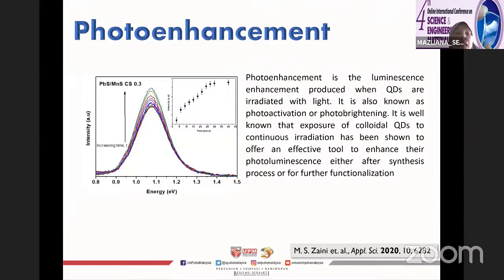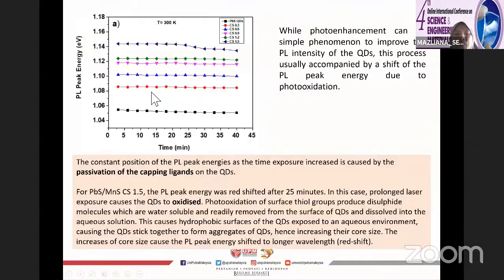samples when we anneal. So we do the photo enhancement. Photo enhancement means you anneal the samples under the laser, and we would like to see the increase in terms of the intensity. And here I just show you the sample of 0.3 monolayer, and by annealing the sample for 45 minutes, we can see that the intensity keeps increasing.